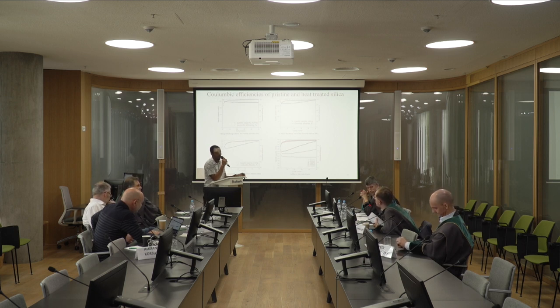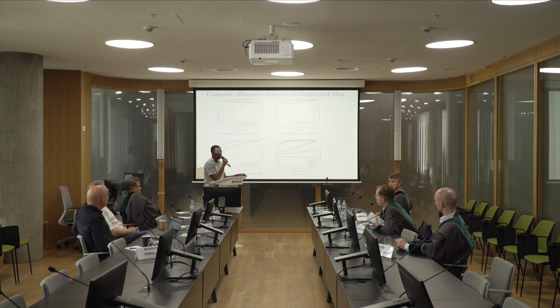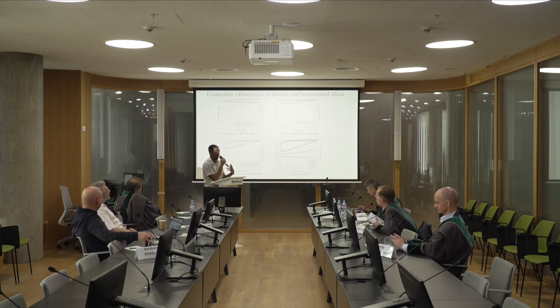Okay, so the next question would be, you propose this silica as a promising anode material, right? But for anode material, in order to operate, you also need to conduct electrons to support the redox reaction, right? But it's known that silica is a good insulator. So how are you going to use it as anode material? So I think we need very good carbon coating, and it's exactly what we're doing now. What we tested here is just uncoated silica in its natural form, but the measurements we're doing now have silicon powders which have been pre-coated with PAN and then prepared as electrode.